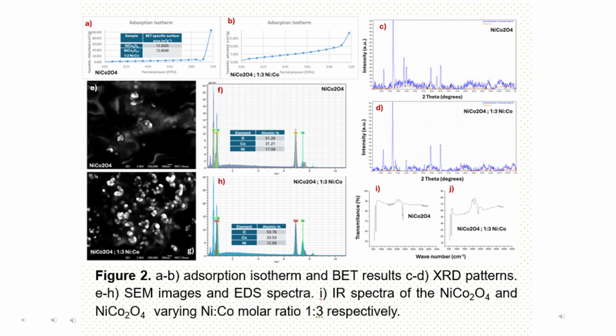EDS confirmed the elemental composition with nickel, cobalt, and oxygen as the main elements, and slight variations consistent with the design of the stoichiometry. The homogeneous distribution of nickel and cobalt suggests the successful synthesis of the spinel phase.